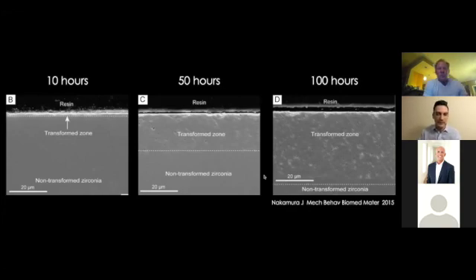The problem is, though, that nobody really has the patience to do these types of studies in real time or do them clinically. We tried to do a study where we had patients wear a zirconia crown for a year with temporary cement, and then we took it out and mailed it to Georgia Tech, and they measured how much transformation would occur on the surfaces of the crowns. And we got some data back. It was like 5% of the surface transformed, or 10%, depending on the crown.